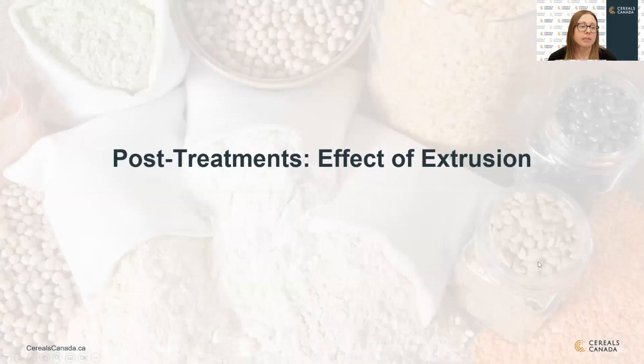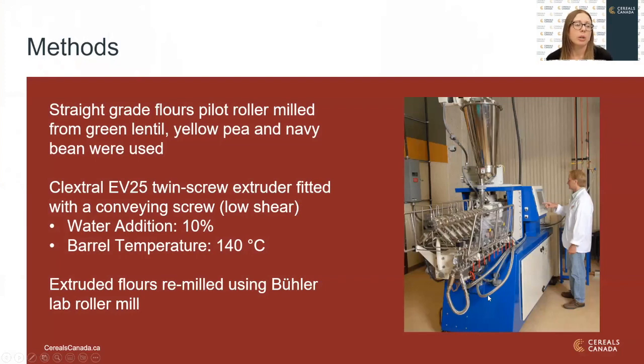So the last activity is looking at the effect of extrusion as a post-treatment. So we took the straight grade flours that we produced from our pilot roller mill for green lentil, yellow pea, and navy bean, and heat treated them through our twin screw extruder. Chickpea is not included here because of its sticky nature. There was a real challenge to try and get it to flow through the extruder properly, so we were unable to process it.